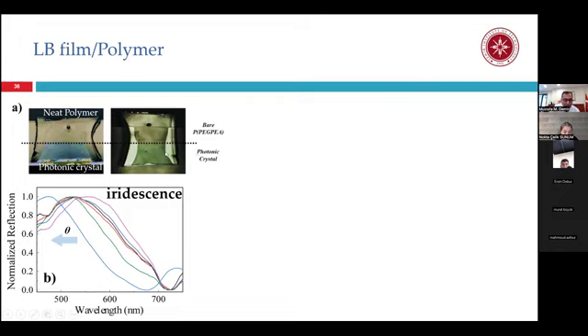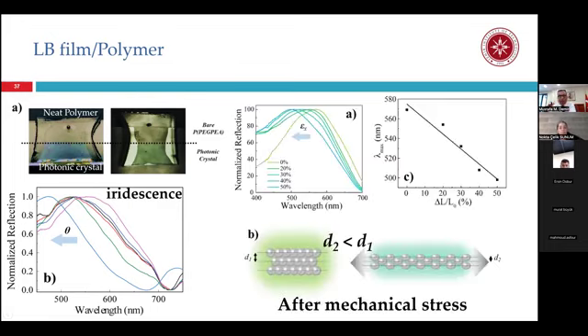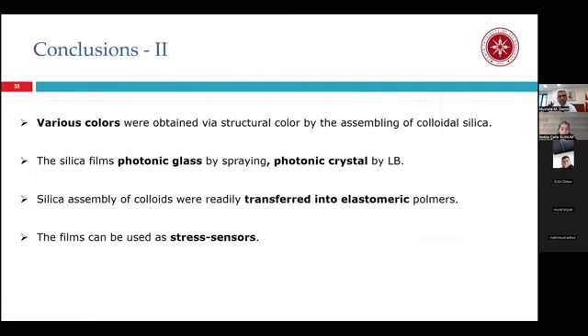Okay, so on the right hand side you see the yellow version of this sample. They are iridescent. When you change the angle, you obtain a different spectrum. The color of the spectrum gives the original color of the material here. So one can follow the lambda max change. The lambda max means the peak point of this spectrum. So depending on the strain, you can readily see the lambda max varies from 580 to 500, and these colors you see on the colloids are the original colors. We have a variation between yellow and, say, green upon application of mechanical stress.